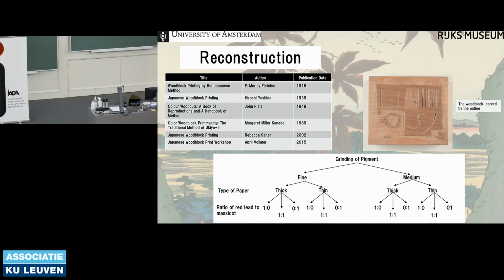While creating this reconstruction, I determined that there were 3 variables that I found really affected the printing process and I wanted to examine further. And these were the thickness of the paper, the amount of impurities in the pigment, which was lead monoxide added by me intentionally, and how finely ground the pigment was.